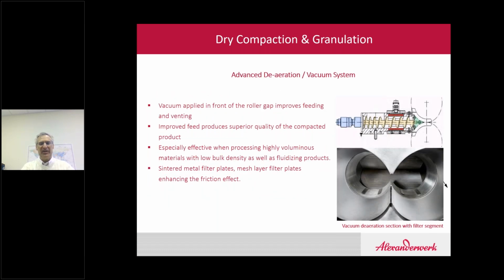Let's take a little bit closer look at the vacuum deaeration system. This is actually a side view from a system that has a dual feed screw setup. You can see the vacuum ports or the vacuum housing right before the roll assembly on the far side of it. It's typically a sintered metal element of very, very fine porosity. That way we're not pulling any product through it into the vacuum filter.